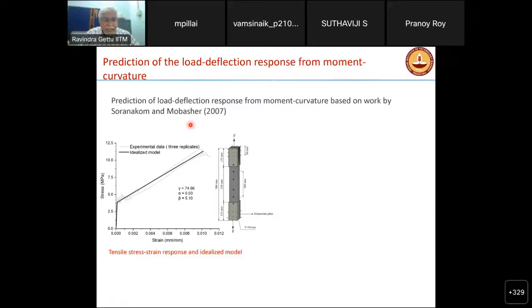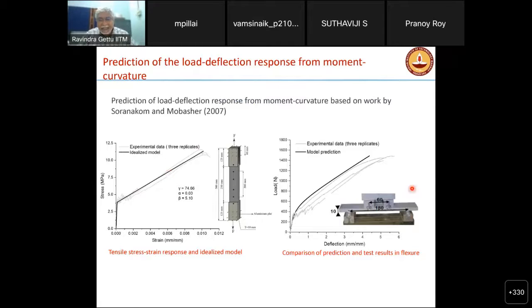There's a lot of work done by Professor Mobasher in Arizona State, where he takes the stress strain behavior of the composite. This is what I showed you before. Like you have a bilinear behavior, we have experimental data, and then you idealize with a model. You take a model and say that this is something that we can use as the constitutive behavior, and then go on to predict what happens, say, in bending. So we have used their methodology and their model, and we predict the experimental behavior. And you see that you get a reasonable fit.